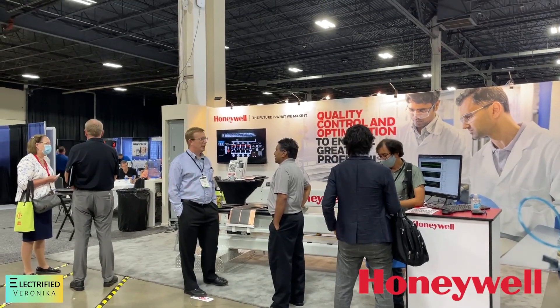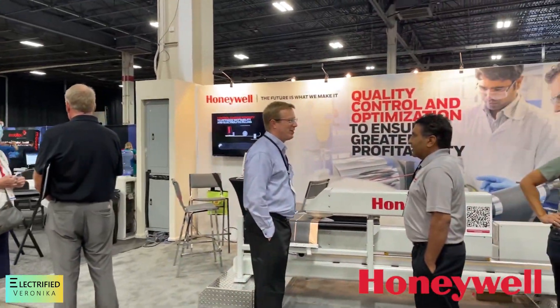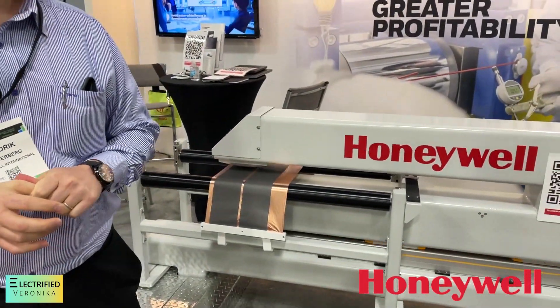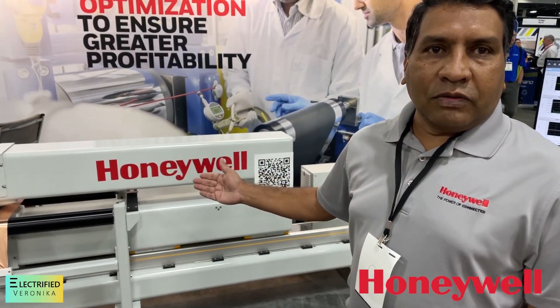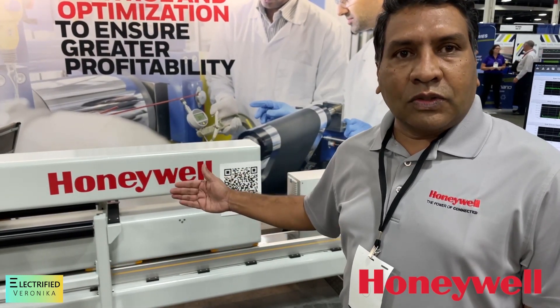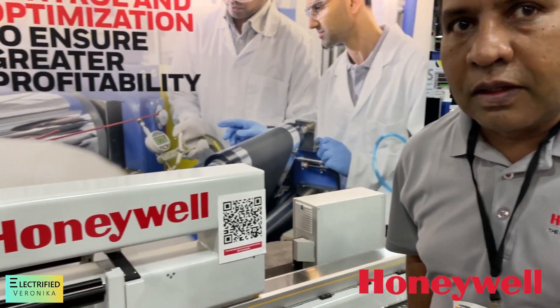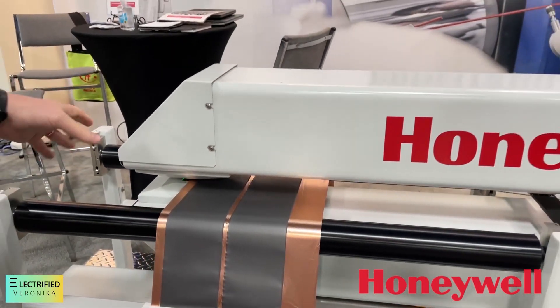I will be talking to Honeywell right now. They have a very interesting and very large sensor. This particular sensor is used mostly in the pressing section to measure the total thickness of the material — one for anode material and one for cathode material in the pressing section. It can also measure in the dry section of the coating. The typical thickness being measured here is around 200 microns, and they measure within around one micron accuracy.